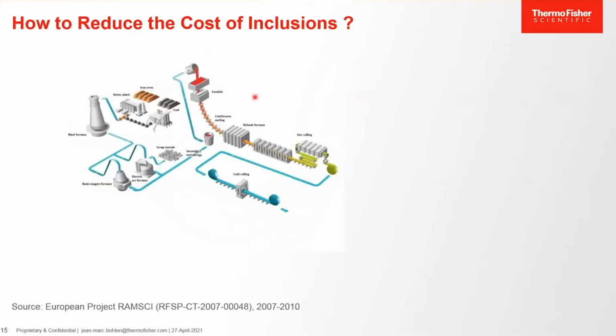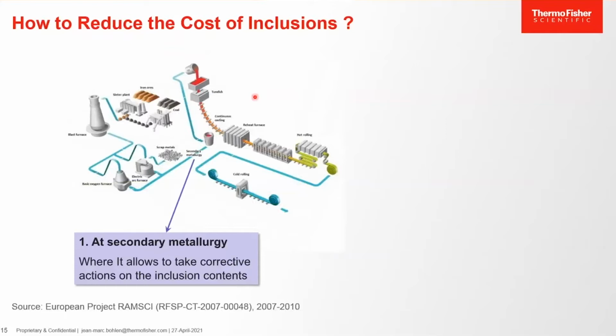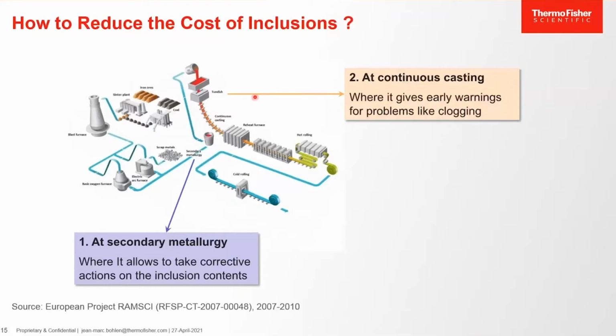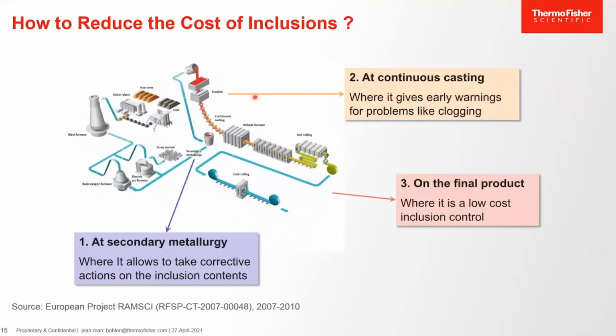The European steelmakers also concluded that the best opportunities for savings on inclusion cost were at secondary metallurgy, where inclusion analysis allows to take corrective action on the inclusion contents. So steel treatments can be adapted in order to correct for bad inclusion contents. Another place is at continuous casting, where optical emission gives early warning for problems like clogging, the problem we've seen just before. And on the final product, where optical emission is a low-cost inclusion control method. So these are the three places where steelmakers recommended to use optical emission inclusion analysis. There are, of course, other possibilities to use this technique.